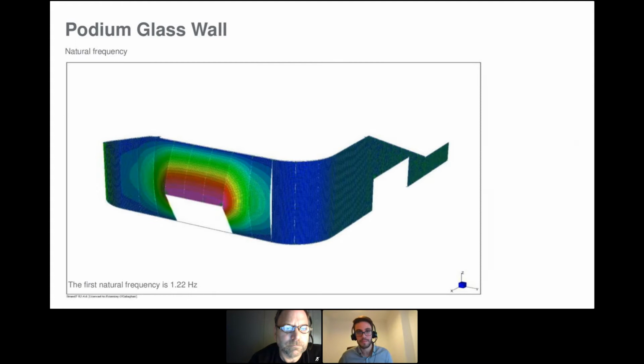Clearly, we have to check also the natural frequency of the facade. So what we can see, and what we expected as well, is clearly that the east elevation, where we have the rocking portal frame, is the most flexible area, having a natural frequency of around 1.2 Hz. And this is still above the threshold set by few codes like the Hong Kong one and also the American one, where above 1 Hz, you don't need to consider some dynamic effect on the structure.